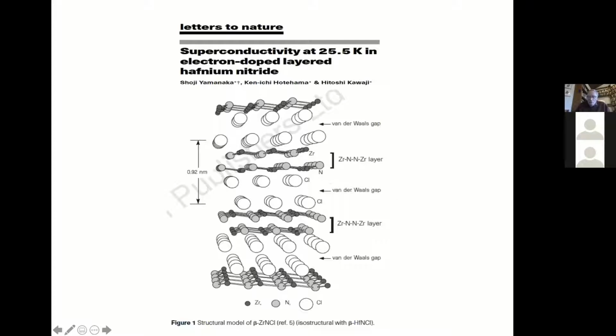As is typical for working with van der Waals bonded layered materials, they're actually fairly easy to intercalate stuff into these layers, and putting lithium in there in this material actually makes a 25 Kelvin superconductor. So you start with what's essentially a valence type compound with van der Waals bonded layers. You add some electrons to it, and it becomes a superconductor.